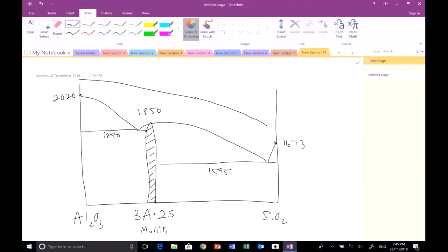But when you heat it for a very long time, if you can't get the temperature, you extend the time and give enough time for diffusion to take place, which would be faster at a higher temperature, but it's slower at a lower temperature because you still get the same extent. But today, if we analyze bricks, we're almost never going to find mullite in them because they're all fired quickly and they want to reduce energy costs. But in those days, well, throw them in a pit and fire them for 3 days, okay.